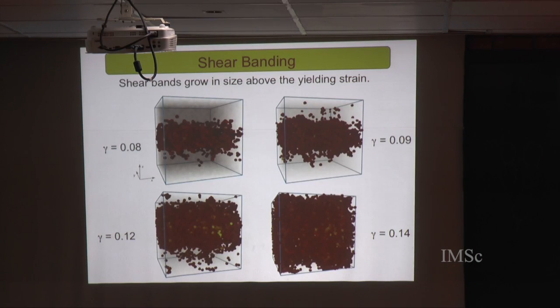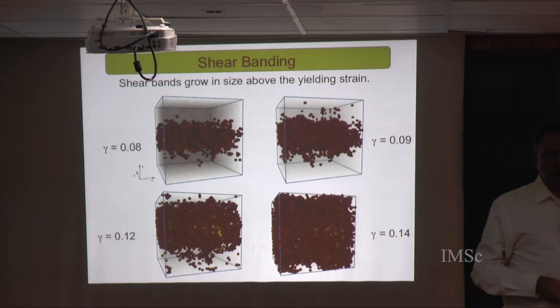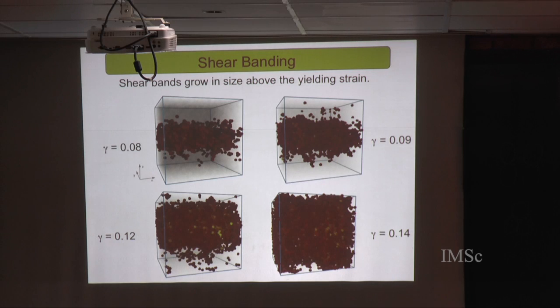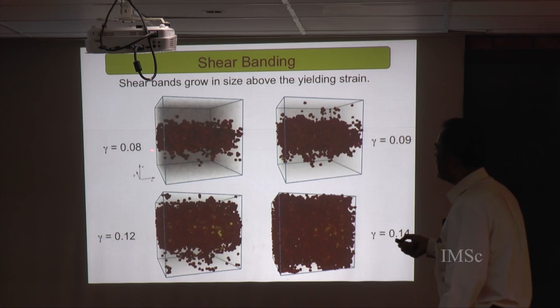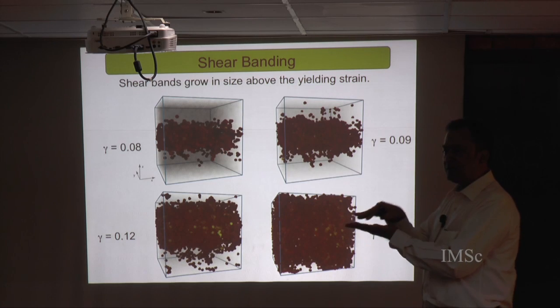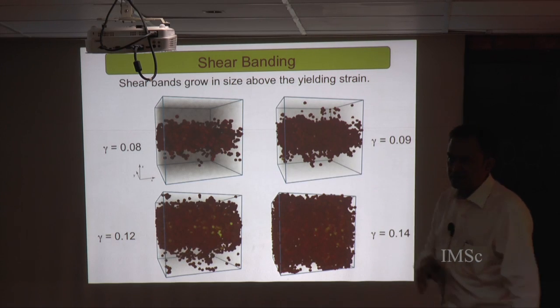If you look at what happens as a function of amplitude going to larger and larger values, you see that these bands clearly grow. We don't go to lower amplitude values, but still above the transition, presumably one can speculate that the shear bands are initiated at the yielding transition and then grow in thickness.